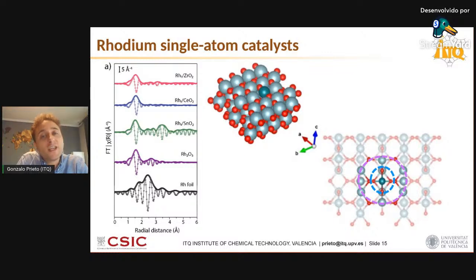It is very important in catalysis to rule out the presence, together with your isolated metal centers, of any other metal entity with higher nuclearity. Because in catalysis, a minority of your surface species may account for the majority of your catalytic conversion. So that's where the challenge stands.